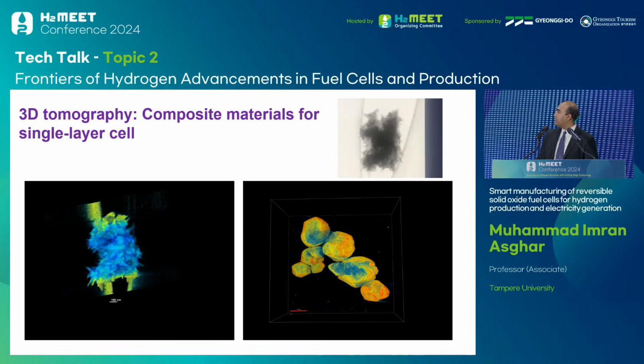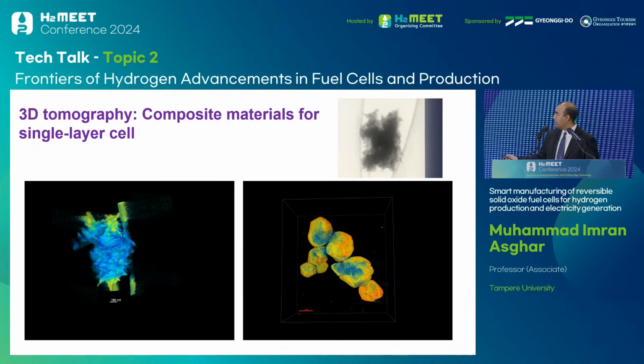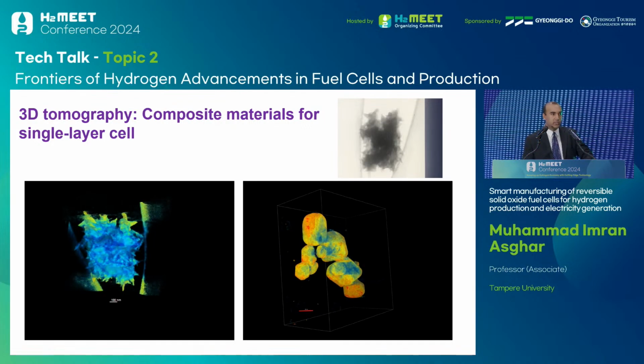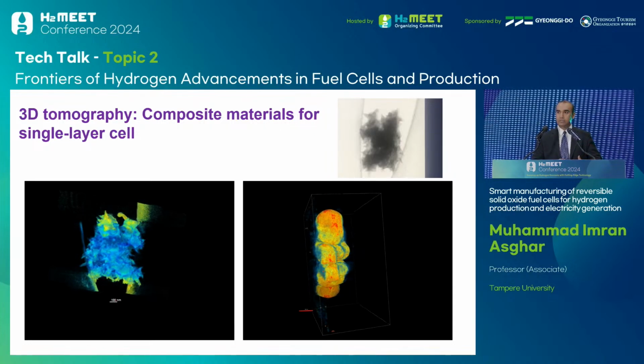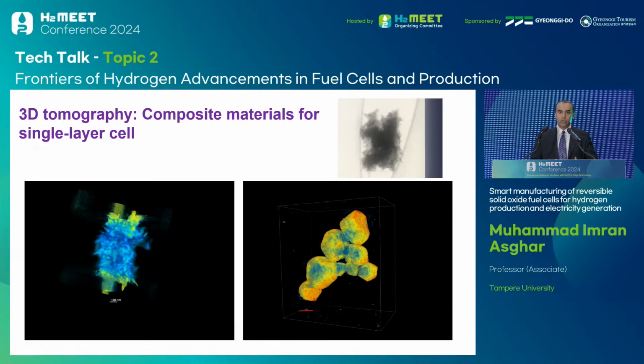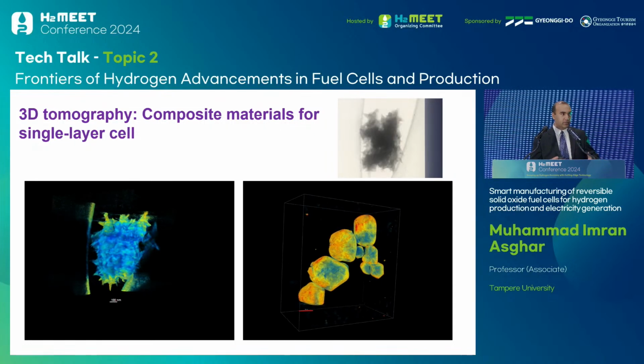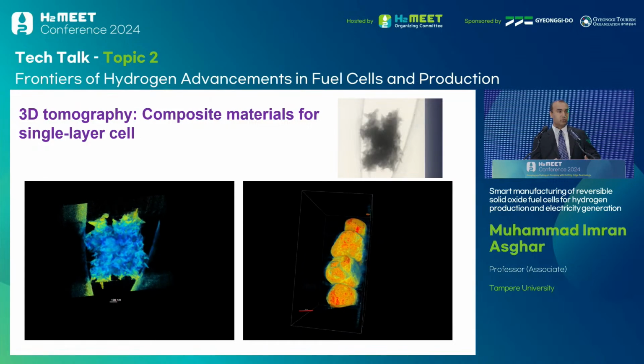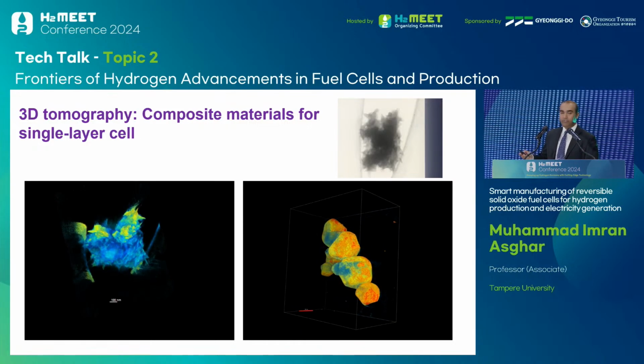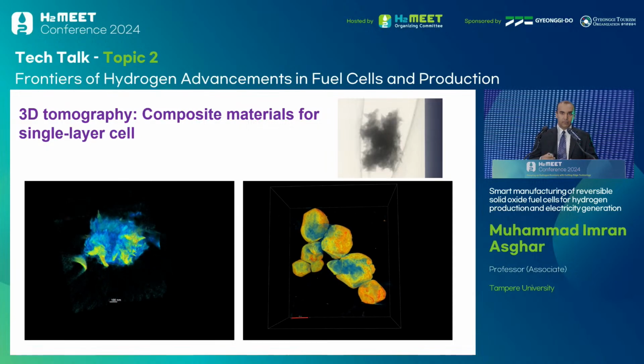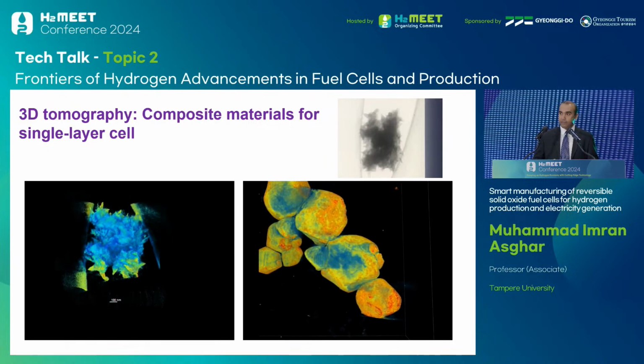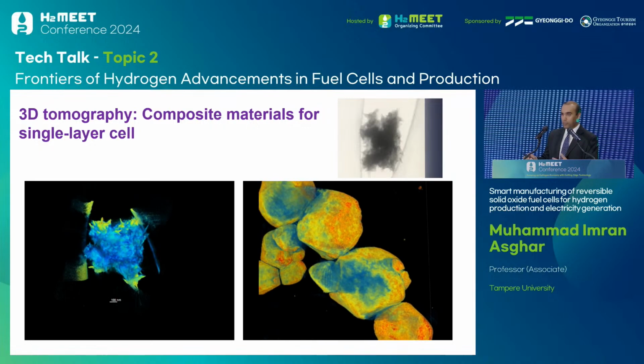So here you see we do 3D tomography on our samples, and we try to study how the interfaces are, because it's very important for these cells to block electronic leakage, because in the single layer cells we have to prevent the short circuiting of the cell. So these interfaces are super important. So we engineered the band levels, energy levels, and we optimize those materials.